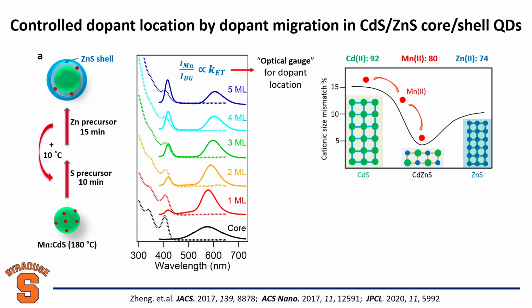So here the manganese has a large size mismatch, too big, but here intermediate, very close to manganese. We think that's what happens, right? We go to the alloy phase with decreased size mismatch, and thermodynamically it should be more stable.